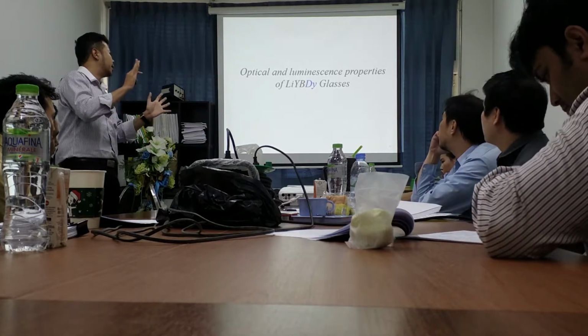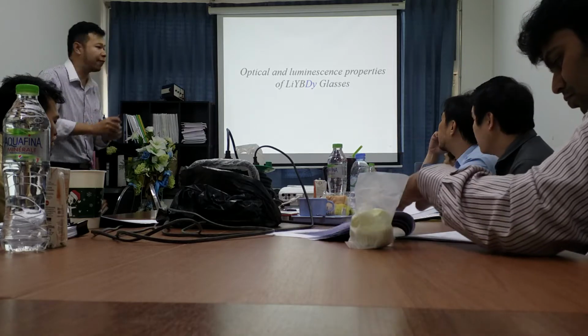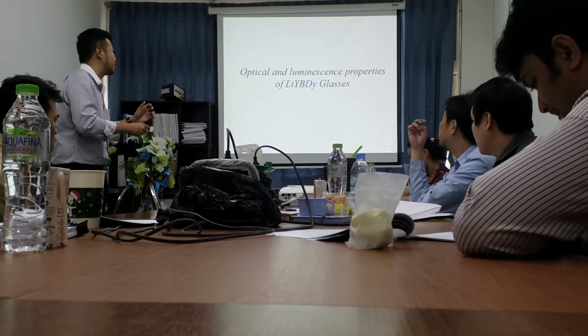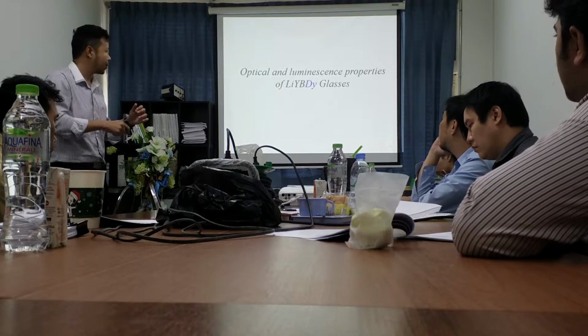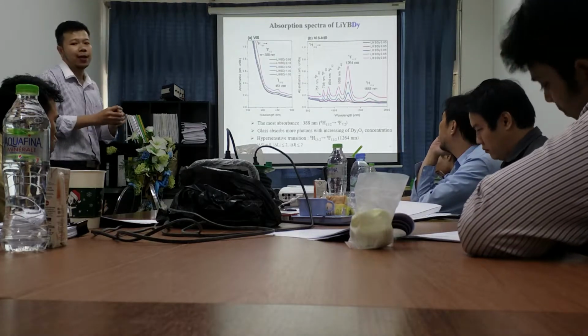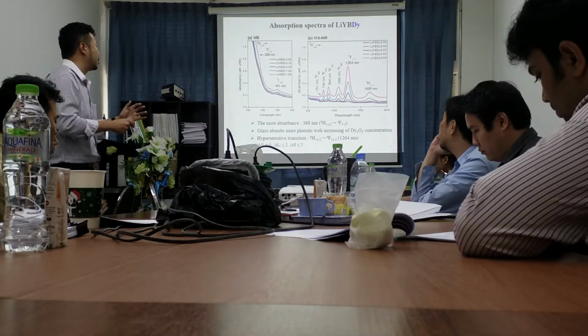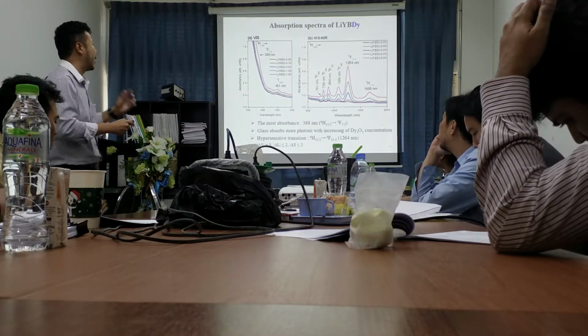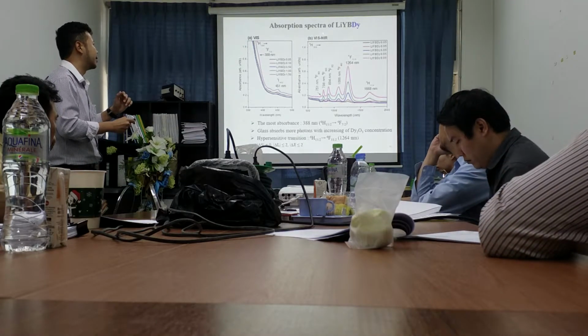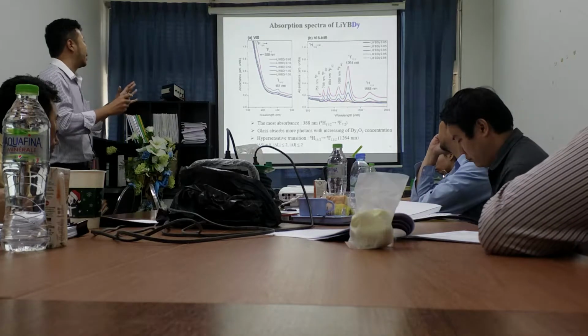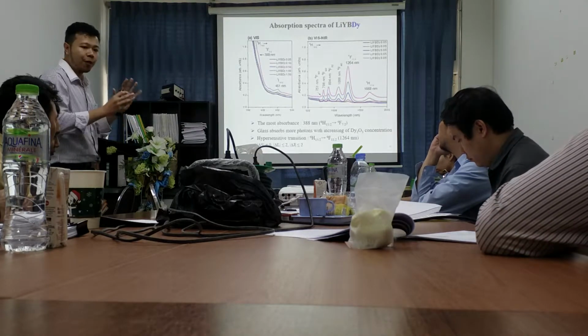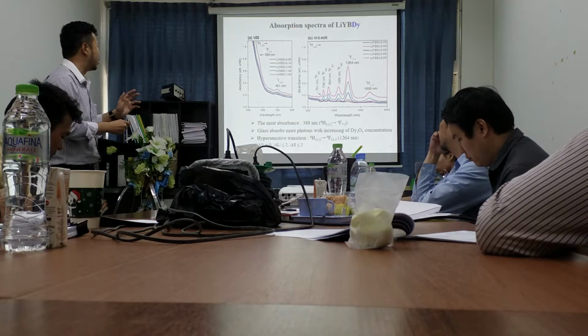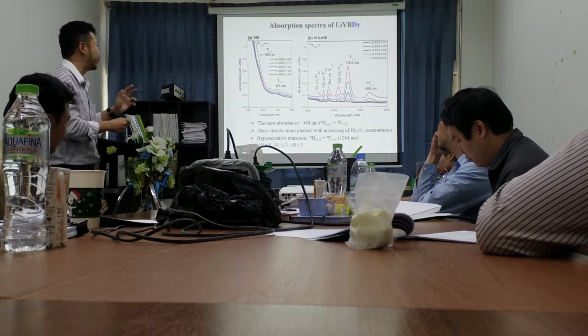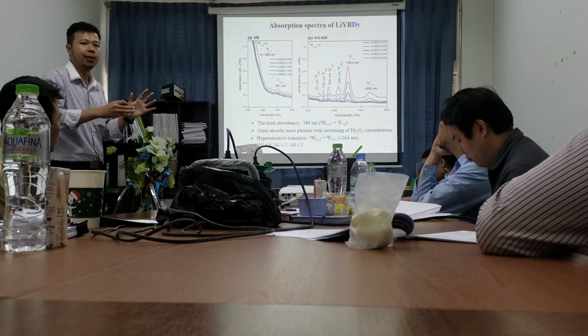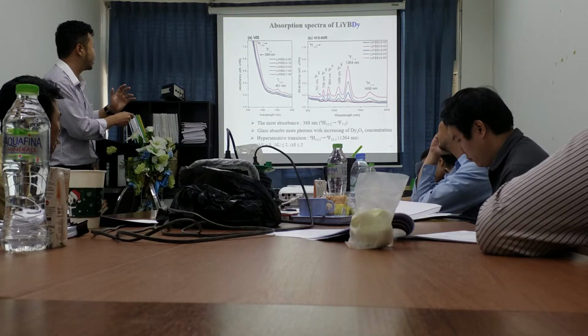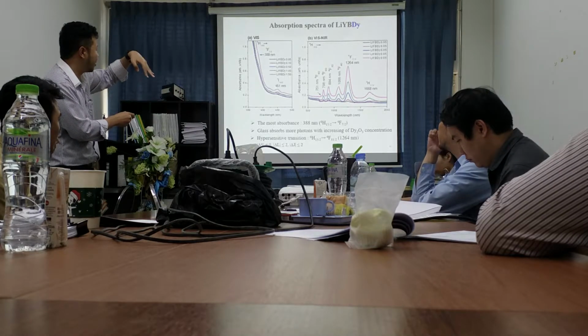Okay, I move on to the spectroscopic results of the first series of the glass, the Dy-doped glass. This is the absorption spectra of the Dy-doped glass. This glass absorbs photons in the visible light and near infrared region. And the strongest absorption band is about 388 nanometers, which is overlapped with the host absorption about here. You can see some curve and some curve here.